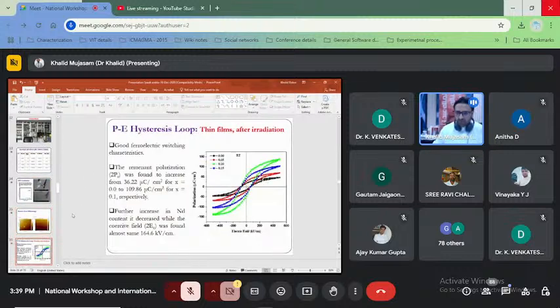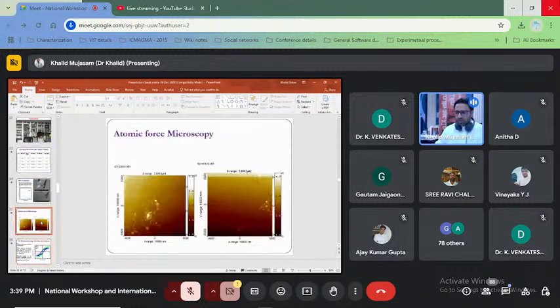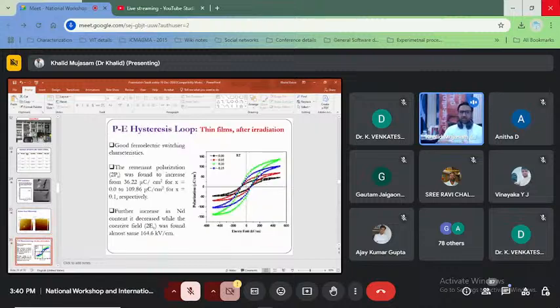So after going through these damages, which are visible also through this atomic force microscopy, it is showing us clear-cut images of how the roughness of the material has changed. This is before and this is after. And what we were looking at was whether we could achieve the S-type loop after the irradiation. Yes, we were able to have some kind of S-type polarization after the tuning of this material. That was a remarkable achievement.